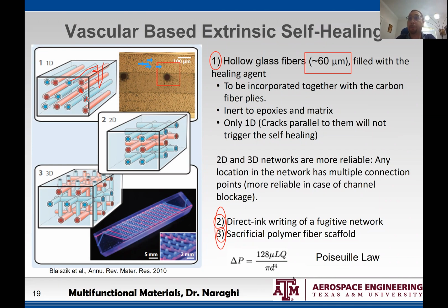And so I have two choices. Either I put them this far away from each other, which is relatively large if you think about it. The ply thickness of a composite is on the order of 100 to 150 microns. These are 200-300 microns apart from each other.